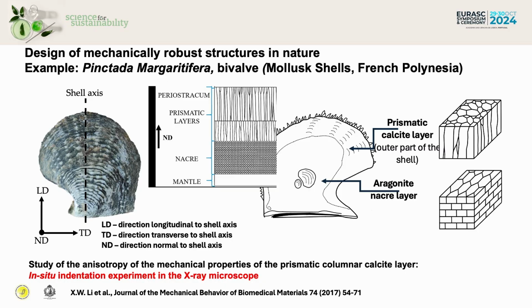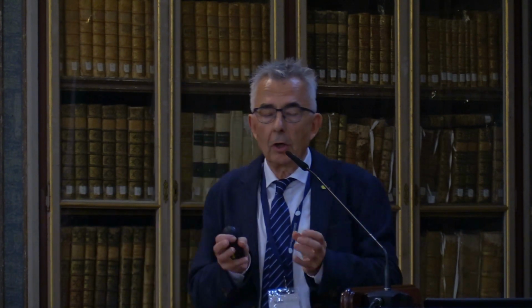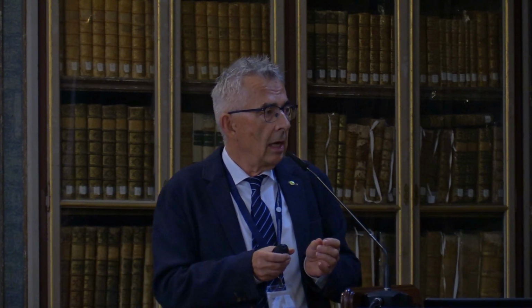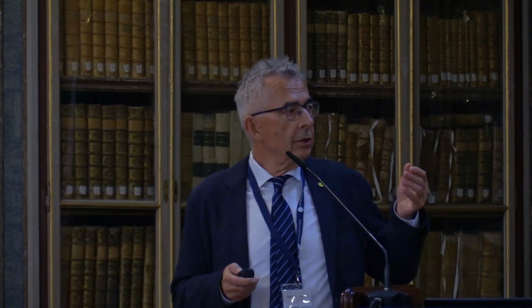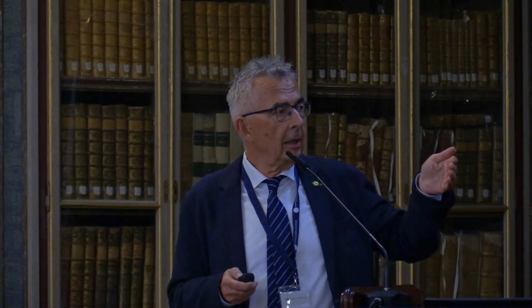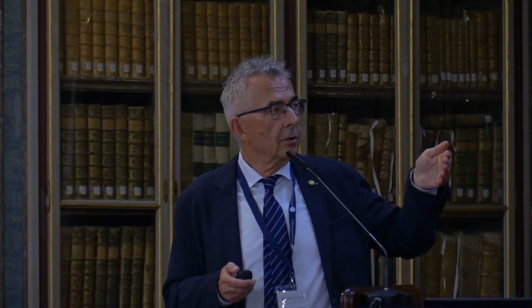Let's come back to the mollusk shell. The outermost shell of the mollusk is such a prismatic structure, and there we have calcite. This is a crystalline element, and then in between there is an organic phase. And we have done an in situ indentation experiment in the X-ray microscope.